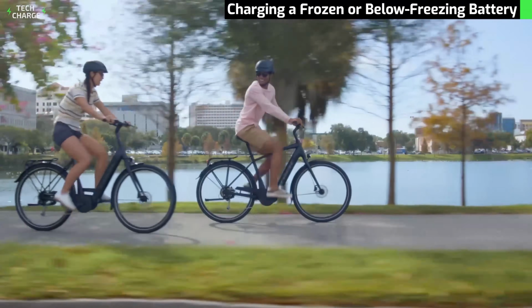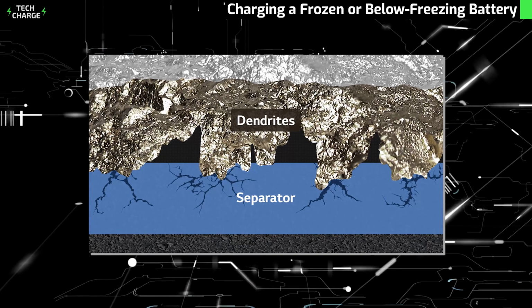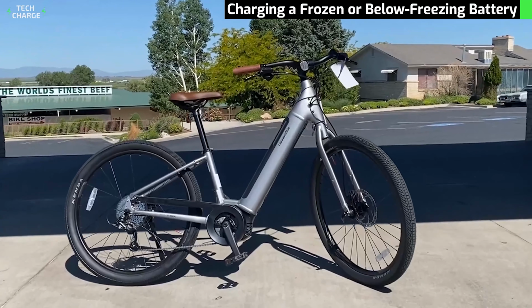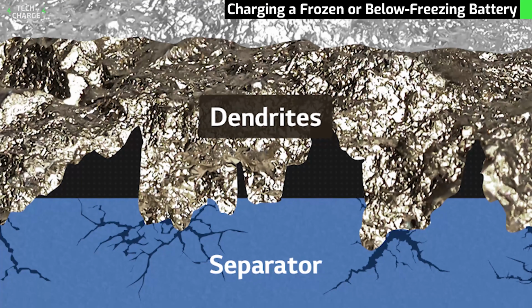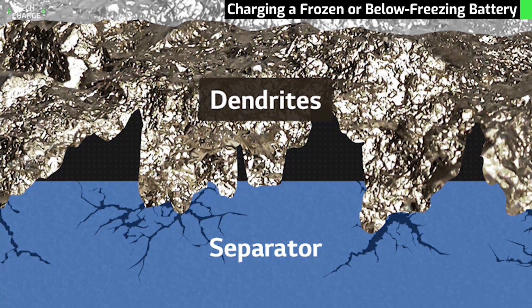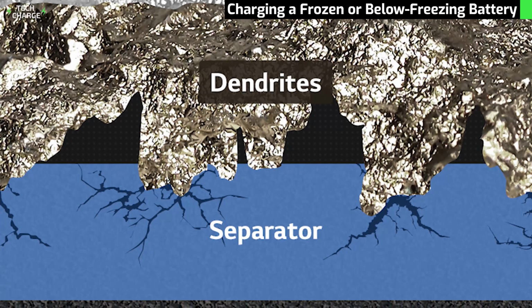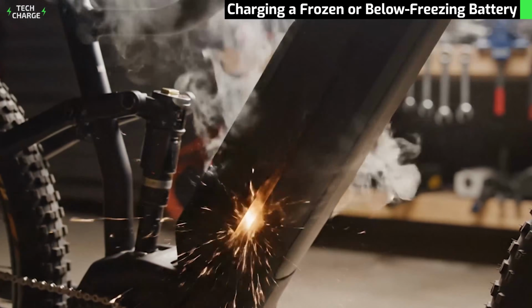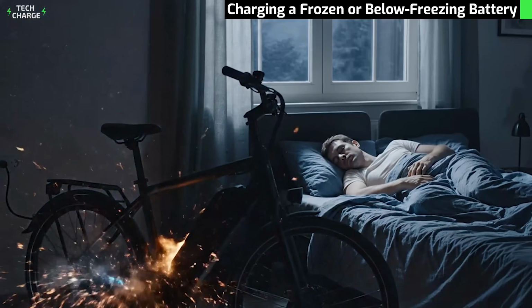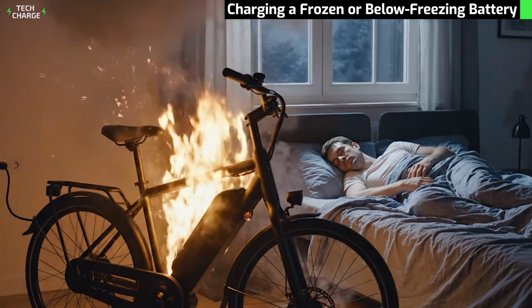But the real danger is dendrite growth. As metallic lithium accumulates through repeated frozen charges, it can form sharp crystals that eventually pierce the separator membrane and short-circuit the cell. This is how internal short circuits develop that lead to thermal runaway and battery fires.